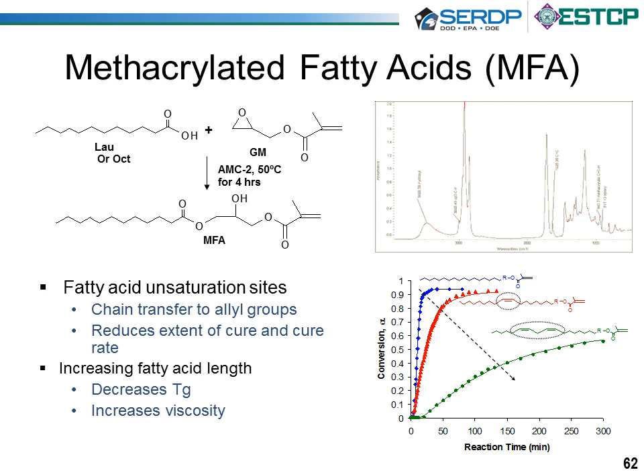Now, there are certain aspects of the fatty acid molecule that are more desirable and certain ones that are less desirable. If we look at that plot of conversion versus time on the bottom right, we see that as we have fatty acids with more unsaturation, this actually affects its ability to cure. So we actually want fatty acids that are saturated, which was found to be ideal. We also found that increasing the fatty acid chain length decreased the glass transition temperature and increased the viscosity, both undesirable properties. But when looking at cost, we basically came to an optimum fatty acid length that balanced the properties as well as cost.